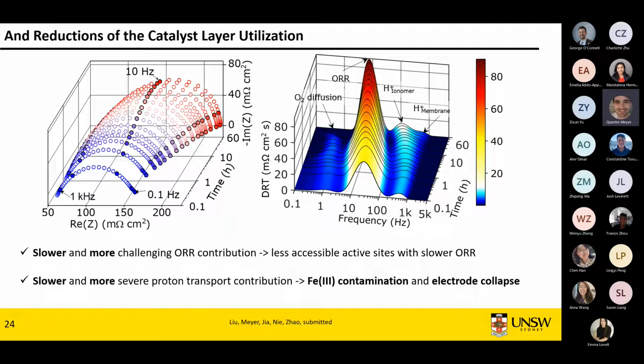There seems to be a lot more processes at low frequency. Here, 10 Hertz was just this region with not much going on. Here, it's over half of the semicircle, which shows you've got a big problem going on. Something is becoming much slower. So we looked at DRT analysis, and we get a much clearer picture.